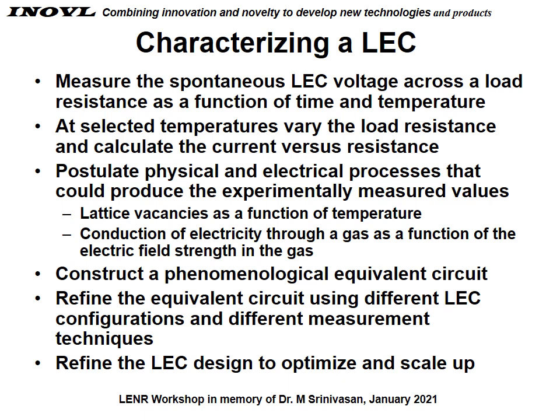We believe lattice vacancies as a function of temperature could be important. Conduction of electricity through gas as a function of electric field strength in the gas. We don't have that much electric field strength in the gas, and yet we still conduct a lot. Construct a phenomenological equivalent circuit, and I'll show you one that we came up with. Refine the equivalent circuit using different LEC configurations and different measurements, and then refine the LEC design to optimize the production of current.